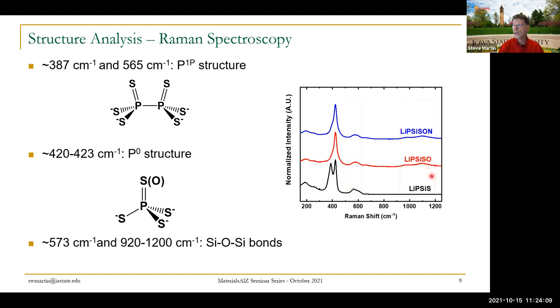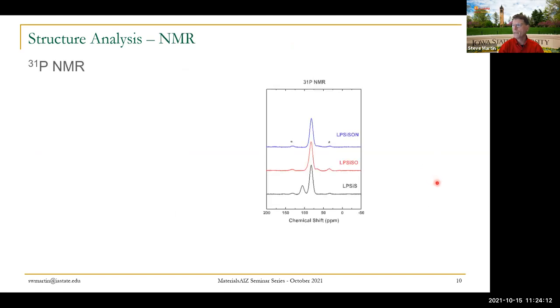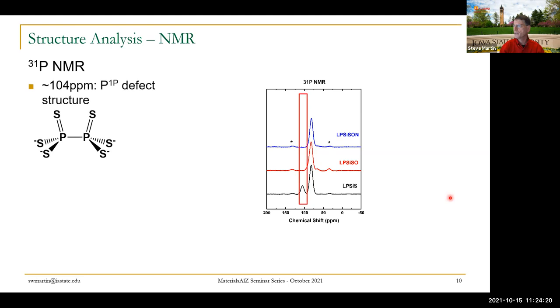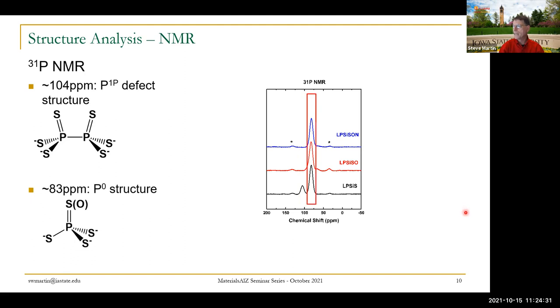We can do a little bit better in NMR spectroscopy. So I'm going to show you two spectroscopies, 31 phosphorus to look at the phosphorus structures and 29 silicon to look at the silicon. Let's start with the phosphorus. As you can see, that defect structure is present in the pure sulfide and rapidly goes away when we get to the oxysulfide and oxynitride glasses, which is a great thing. Somewhat unexpected, but a great thing, the oxygen reacts with that to form a normal phosphorus-oxygen-phosphorus linkage. So we can identify the P0 structures.